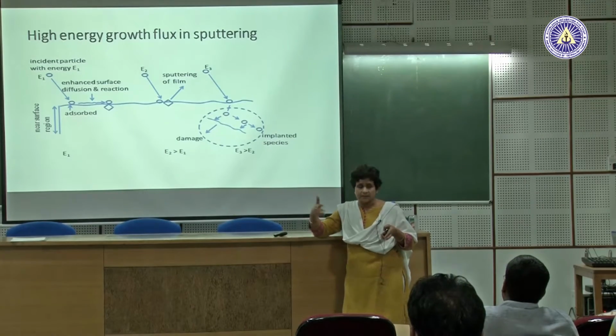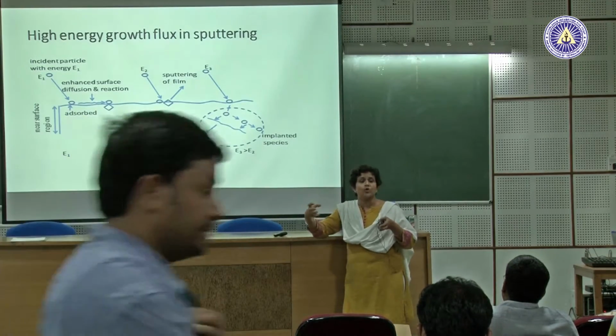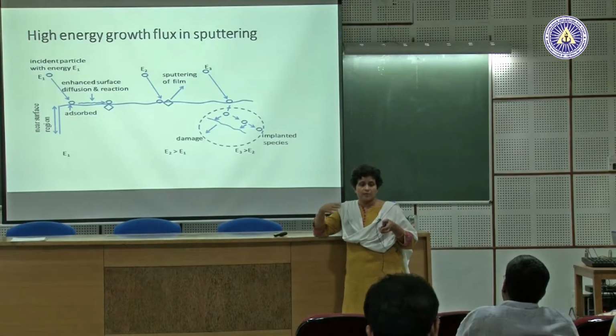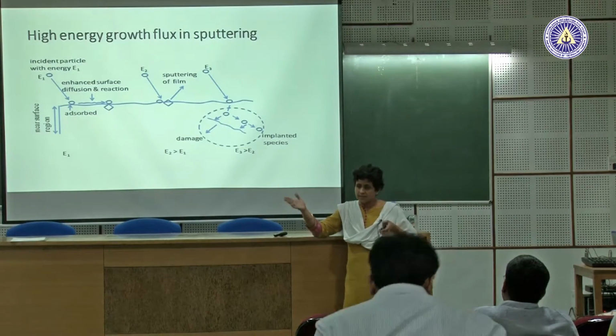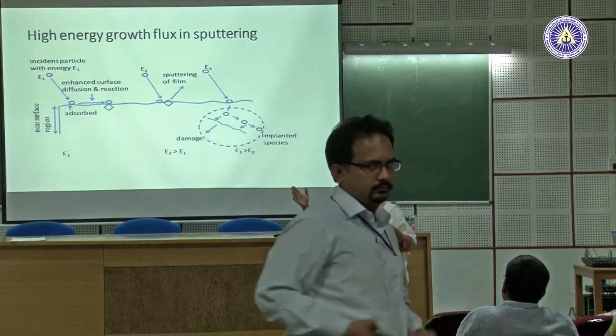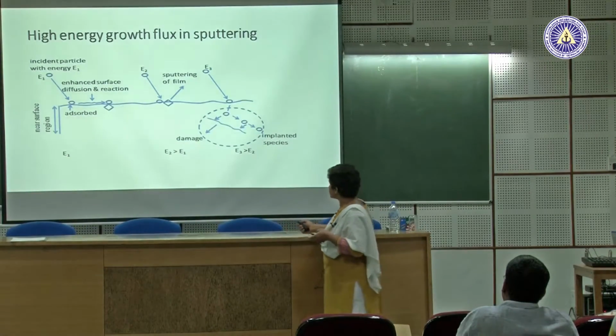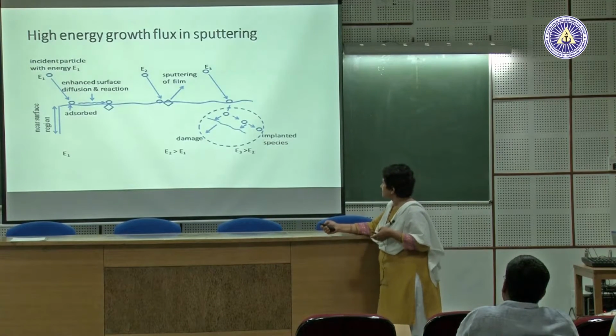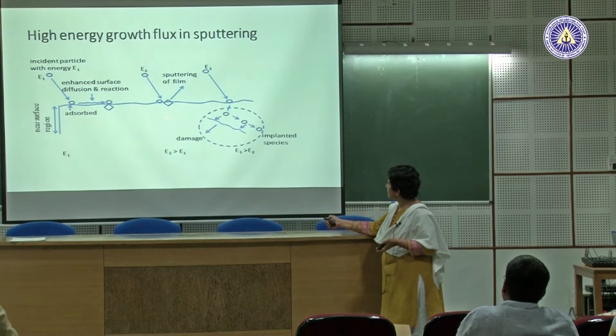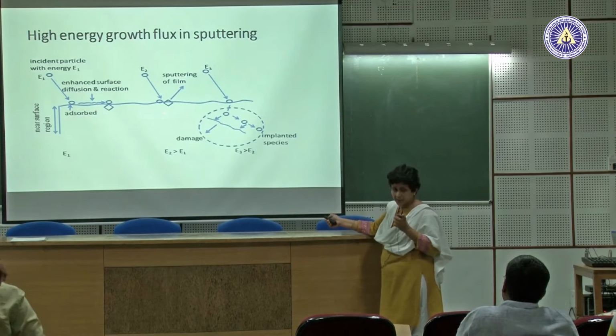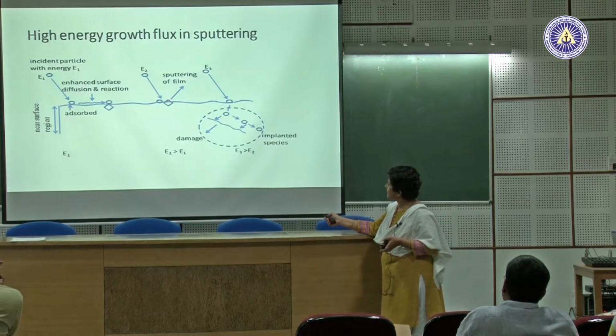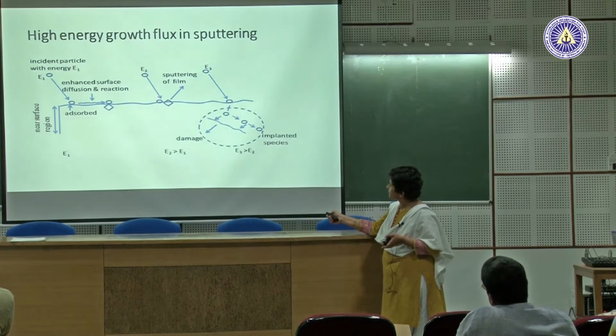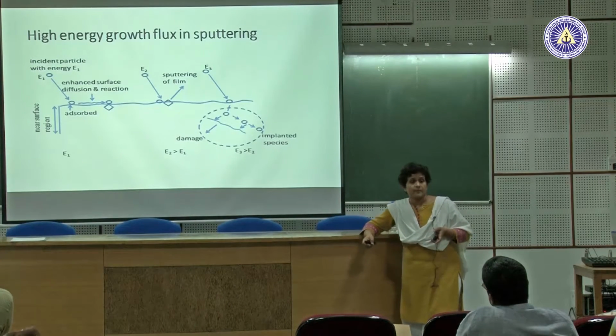Okay? Now that's the power of thin film deposition and the control that you have on the microstructure of the material that you are making. By changing just the substrate temperature, I can go all the way from amorphous to single crystalline silicon. Okay, so that's the enhanced surface diffusion. Another thing that can happen during sputtering is, let's say some materials get deposited, but the atom which is coming to the substrate now has high enough energy that it can sputter the material also, right?